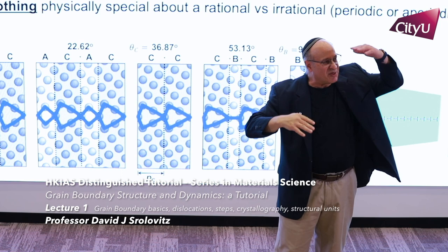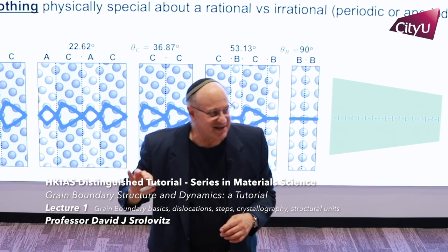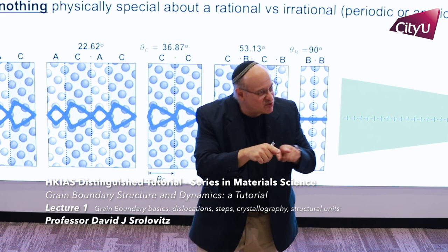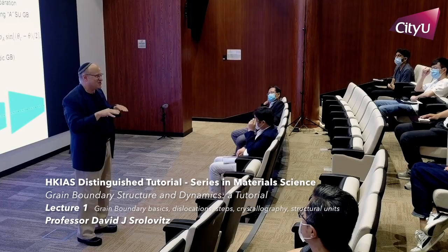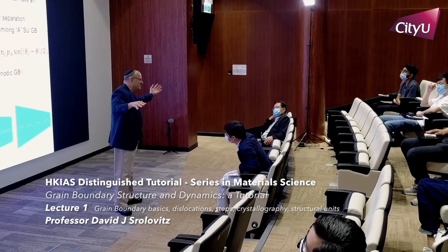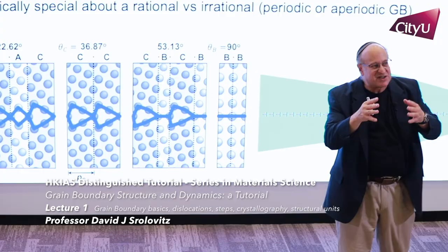You know, so the combination could be irrational. And most grain boundaries are irrational, which is to say the structure is not truly periodic. It could be nice and periodic for a long distance, and then you have to have one extra dislocation, and then nice and periodic again, and then one extra dislocation. If it's not arranged in a regular way, we call this an irrational boundary